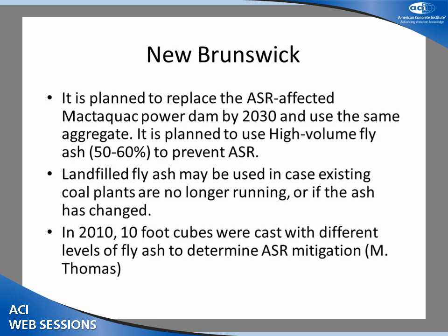Now, related to this, or a similar thing, Mike Thomas has been looking at a structure out in New Brunswick where they've got a dam that needs to be replaced because of alkali silica reaction. They're planning to do it about 15 years from now. But one of the interesting things there, which relates to what Tom said, is that the power plants that are producing coal ash there now may not be in operation in 15 years. So they've got landfill deposits, and they've actually excavated some of the landfill ash and used it to evaluate its performance to control ASR, if they need to rebuild this dam, because they're likely going to have to use the same reactive aggregate because of the volumes and the locality.